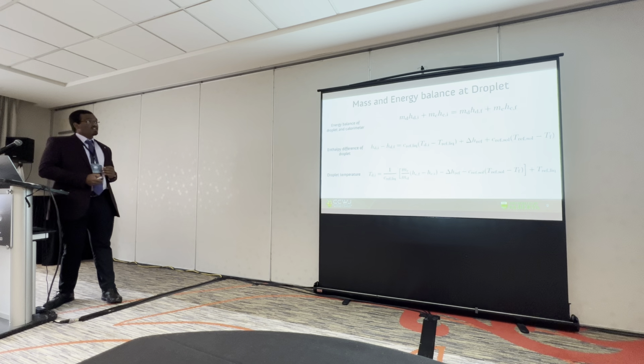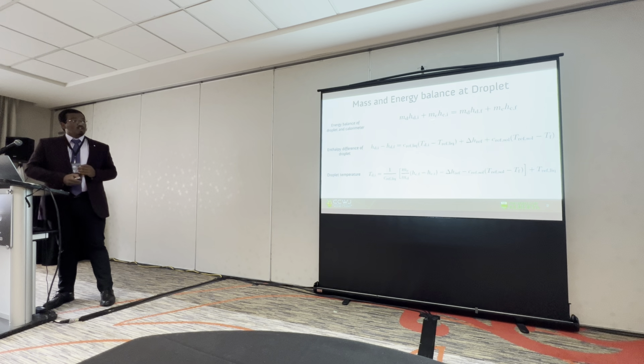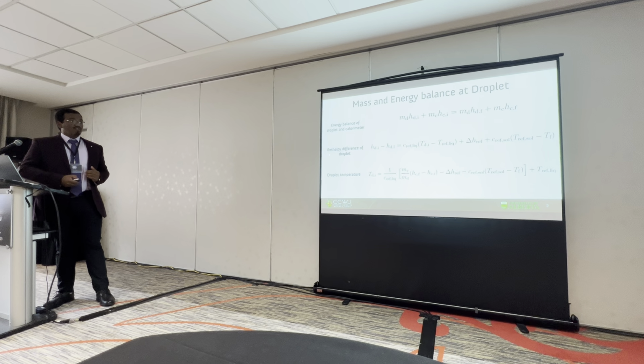Based on that, we have the energy balance of the droplet and calorimeter shown here, from the initial stage to the final stage. Then we are also able to find the enthalpy difference of the droplet, initial and final. So based on all of them, we are able to get the actual droplet temperature TDI, which is based on the enthalpies, specific heat, and the final temperature of the calorimeter as a whole.